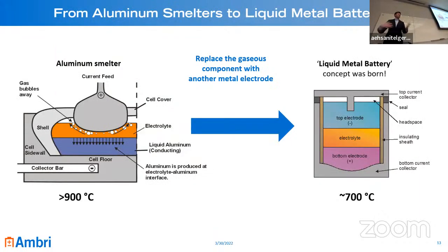So we replace a gaseous component with another liquid layer. And so the original concept was a 3-liquid layer battery that could charge at extremely high power rates and current densities, and then discharge back into the grid. And that's where the liquid metal battery concept was born.